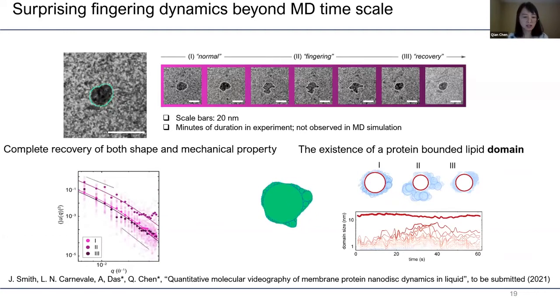And lastly, the nanodisc can always keep a domain about 10 nanometers in size. We attribute this domain size to the strong lipid protein interaction, because the membrane protein in the middle can hold very tightly the surrounding lipid molecules, even during this very vigorous shape transformation of fingering.